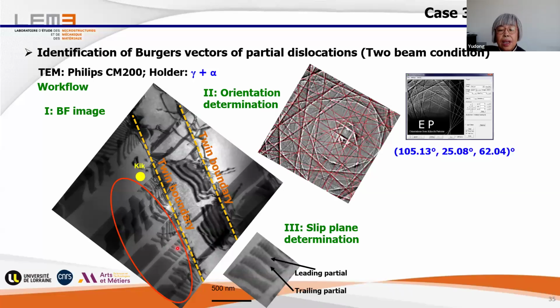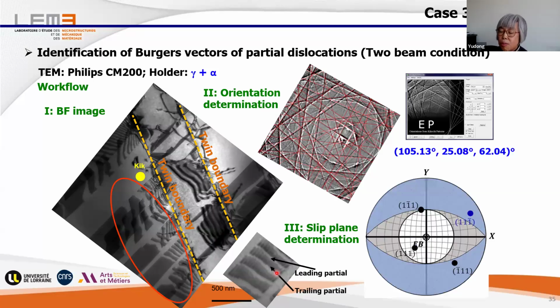Then we first identify the slip plane. And with this, we use trace analysis. And we know for FCC, the stacking faults or dislocations are always on the 111 plane. And so we just need to plot the 111 pole figure. And you see, for these pileups, we can see where the 111 plane trace is. You see, it's here, the trace. And so this 111 plane is inclined in the sample. And so we see the upper line and lower line.